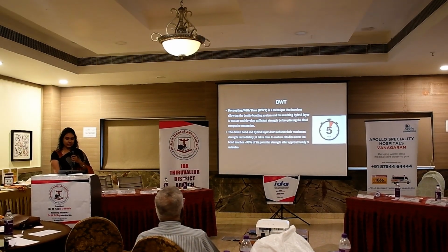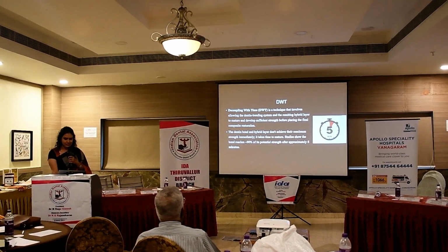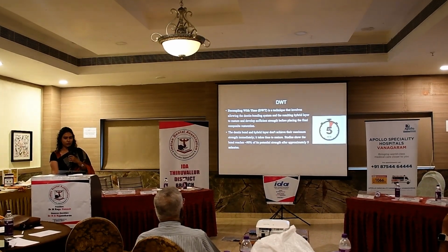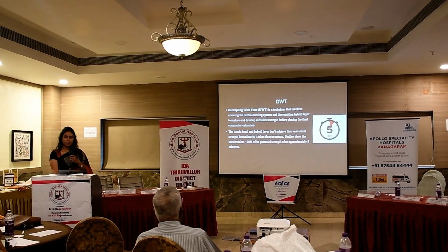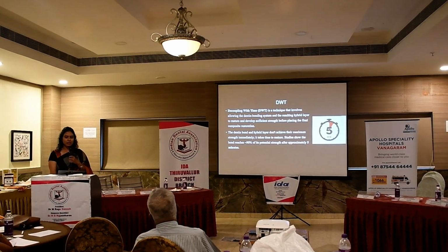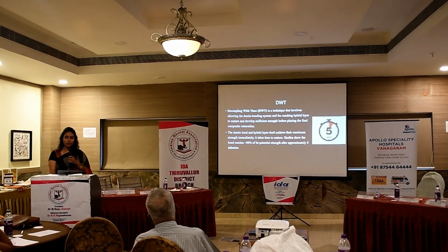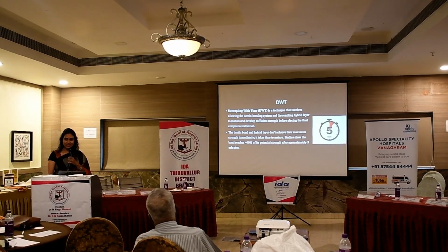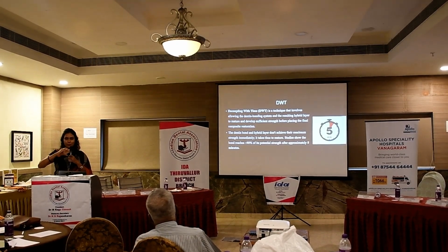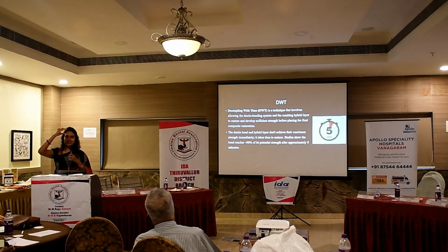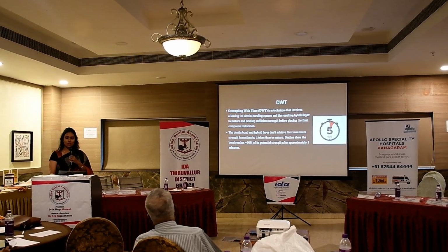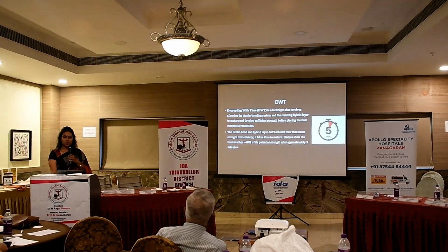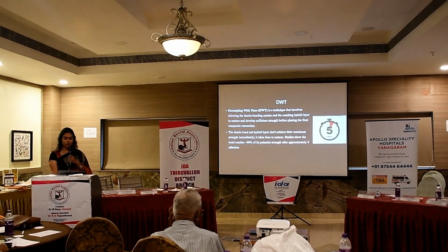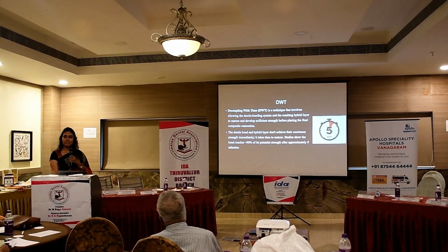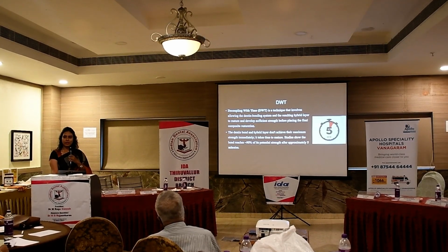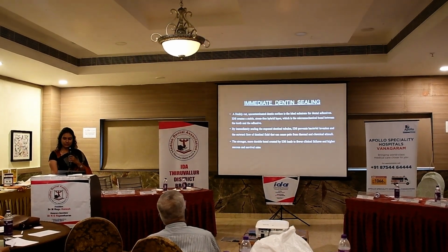Decoupling with time is a technique that involves allowing the dentin bonding system and the resulting hybrid layer to mature and develop sufficient strength before placing the final restoration. The dentin bond and the hybrid layer don't achieve their maximum strength immediately. So it takes time to mature. Studies show the bond reaches 90% of its potential strength after approximately 5 minutes. That is why we give 5 minutes. This gives you the biobase.